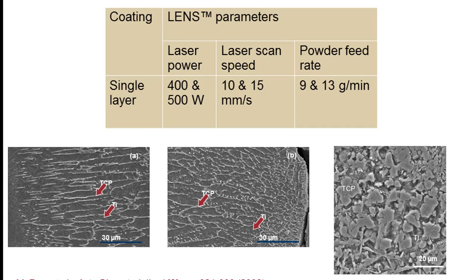We fed calcium phosphate powder from one of the hoppers, doing it on top of a titanium substrate. You can see when we do that, we get these calcium phosphates on the columnar grains, and if you look at the outer surface, going to the absolute outer equiaxed grain region, this top surface shows all calcium phosphate pockets, and because it's an etched surface, we have already etched the titanium. So we can make a very nice, homogeneous, strongly adherent material that's almost not a coating, it's almost like a composite of titanium and calcium phosphate.